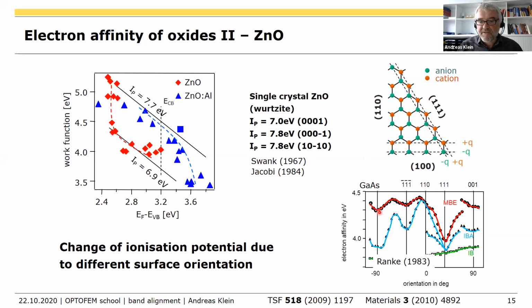And that's also something which has been measured for gallium arsenide. You see the anion terminated 1-1-1 surface has a much higher ionization potential than the cation terminated 1-1-1 surface.